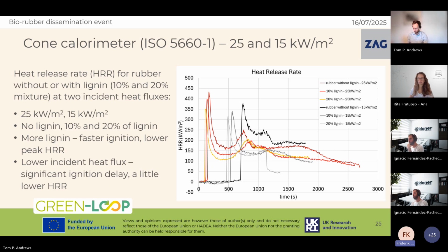Initially, one would expect that lignin, being an agent for intumescence, would strongly improve reaction to fire properties of the material, but this is actually not the case because the lignin as such still burns, and intumescence helps if it is applied to the outer side. We'll see that in the last slide, but not in any application of the lignin into the material. Yeah, so I've commented on this. Next slide, please.